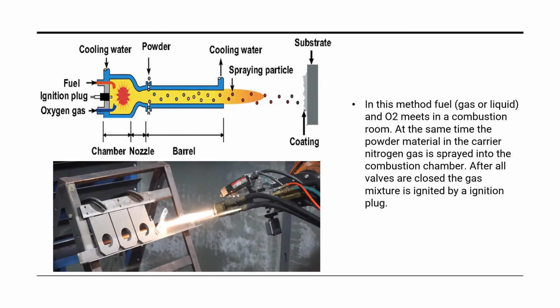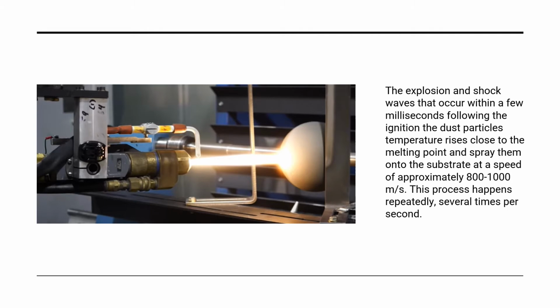Okay, but how does it work? In this method, fuel, which could be a gas or liquid, and oxygen meet in a combustion chamber. At the same time, the powder material in the carrier nitrogen gas is sprayed into the combustion chamber. After all valves are closed, the gas mixture is ignited by an ignition plug. With the explosion and shock waves that occur within a few milliseconds following the ignition, the dust particle temperatures rise close to the melting point and they are sprayed onto the substrate at a speed of approximately 800 to 1000 meters per second. This process happens repeatedly several times per second.